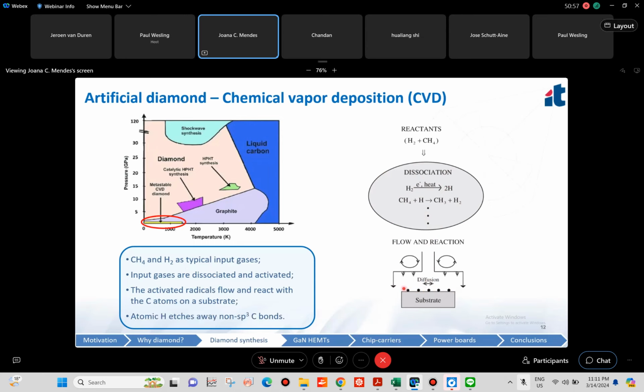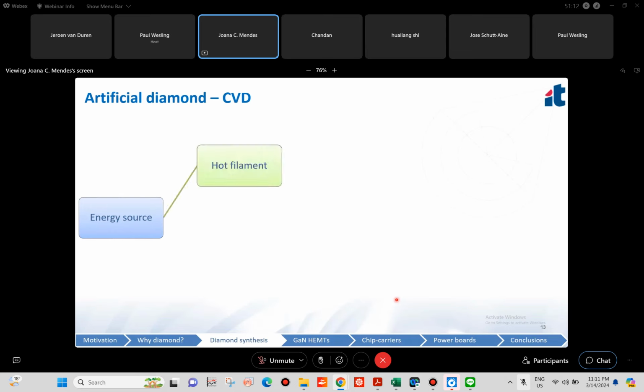And then we have atomic hydrogen in excess, and this atomic hydrogen will etch away the non-sp3 bonds. So in the end, we'll have a closed film, mostly diamond, that is covering a substrate. And depending on the energy source, we can use hot filament, we can use microwave power and supply it through a waveguide, or we can also use microwave power, but use an array of linear antennas.